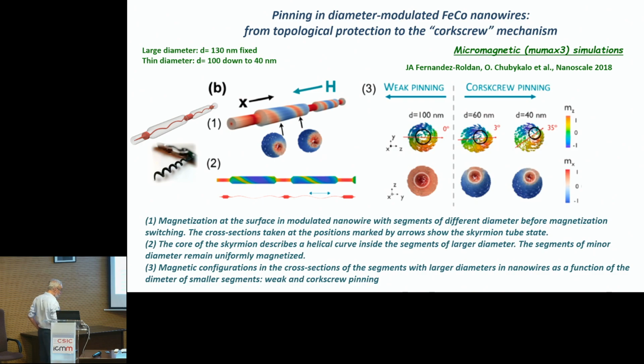Also, particularly Oksana has been supervising all these micromagnetic simulations aspects, and Jose Ángel Fernández Roldán, they did a number of micromagnetic simulations in these diameter modulated nanowires. It was possible to identify the presence of skyrmion tubes from the micromagnetic point of view, where the axis of the skyrmions is not always completely in the center, but is making some helical motion along the length of the large diameter segments.